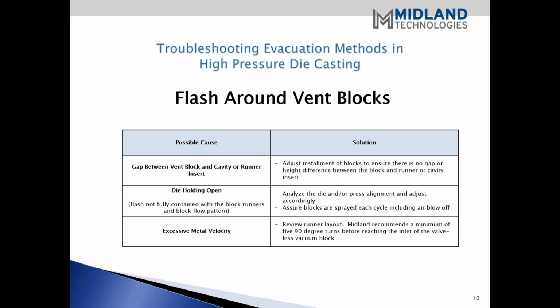And to assure that you're spraying, as I mentioned, and then also that you're blowing those blocks off. If you don't remove the flash up there and you paint over it, you drop it. Same thing happens on the insert. I've seen dies, and we see shots a lot of times with excessive flash in different areas of the tool. Obviously, that's an indication that the tool isn't square, may have gotten peened over. Something's occurred that is not allowing it to be clean. So it goes back to that.